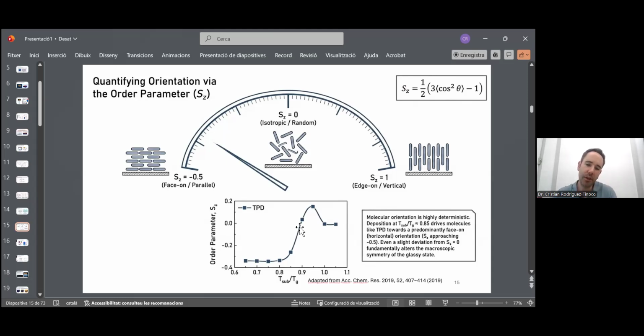Now, we can continue decreasing the substrate temperature. If we deposit the glass at 0.9 Tg approximately, we again have an isotropic glass, okay? S equal to 0, which means completely random. And then if we decrease the temperature, we enter a regime at low deposition temperatures where the S parameter is like minus 0.35 approximately, which again means that the molecules are not perfectly aligned parallel to the substrate, but there is a significant degree of orientation in that direction, okay? And this is very important for many properties, as we will see afterwards, okay?